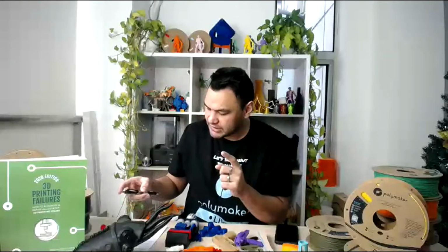What's going to happen is the nozzle is going to heat up the material that you are extruding, and through that material, it will heat up the layer you are printing on, and actually it will heat up all the layers below it. And then this will allow the polymer to stick to each other. So that's the first one. Let me erase that topic. The first one is temperature. The higher the temperature, the more you will create entanglement, the higher the layer adhesion.